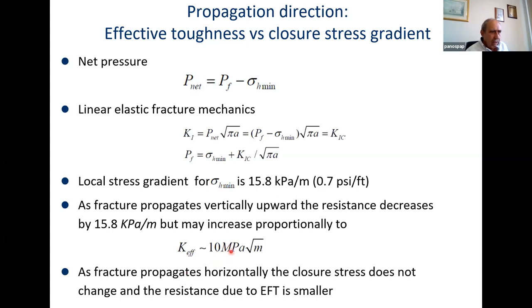So the conclusion is the fracture will propagate horizontally. Actually, if the fracture propagates horizontally, the closure stress does not change, and the resistance, the effective fracture toughness, is smaller. So it's very likely that the fracture will prefer to propagate horizontally.